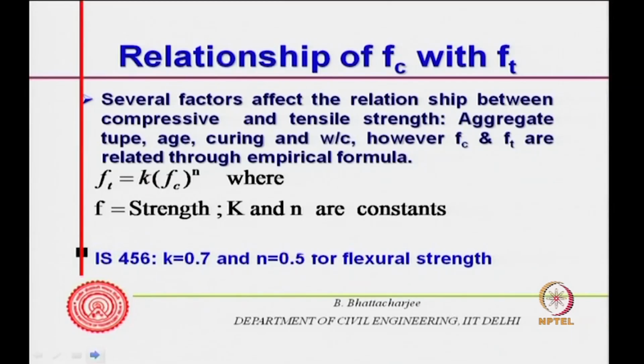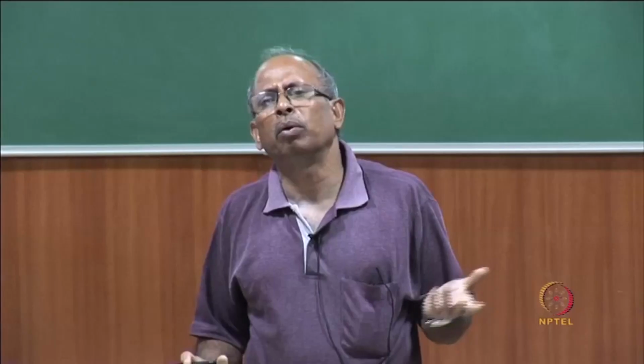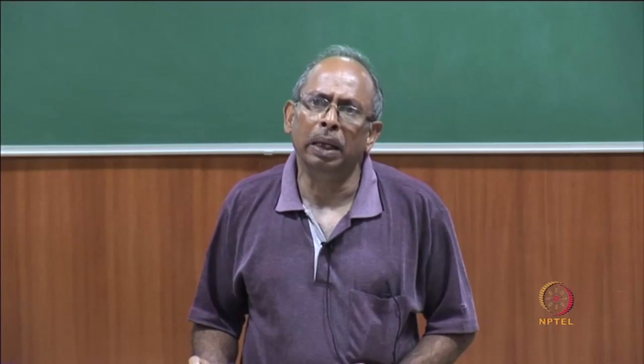Okay. So, IS 456 of course says K equals 0.7 and n equals 0.5 for flexural strength. So, F t is given as 0.7 under root F c k, where F c k is not F c, but the characteristic strength. So, this is largely for design purposes, a little bit of conservative value it would be. So, for design purposes, this is what the Indian standard code gives you. All other codes have similar sort of formulae available.